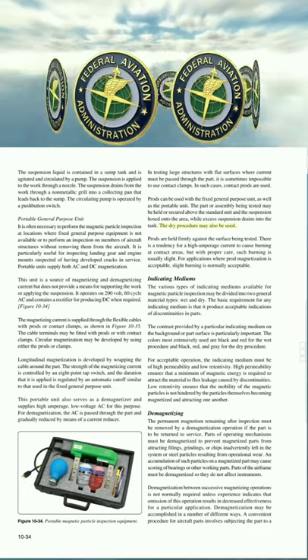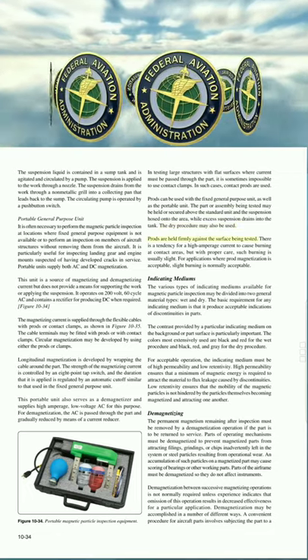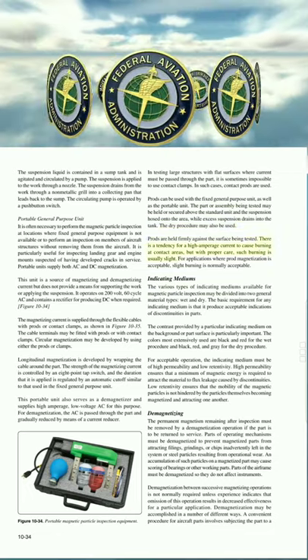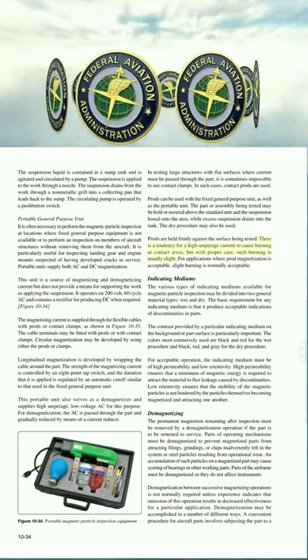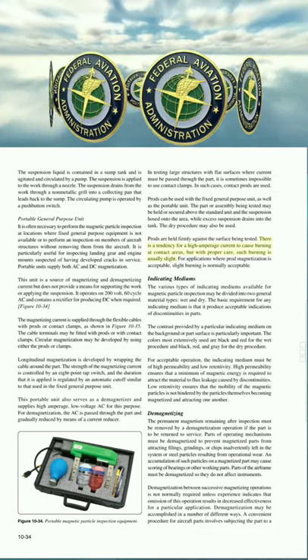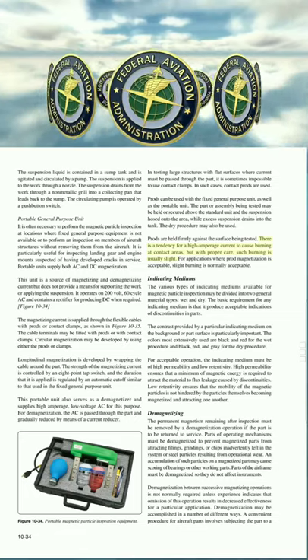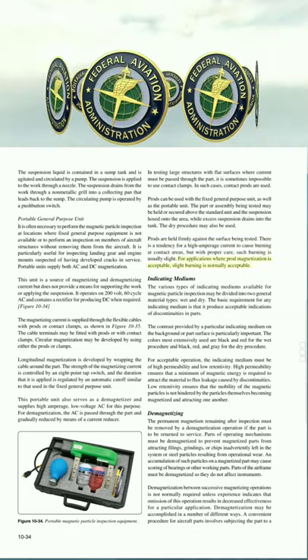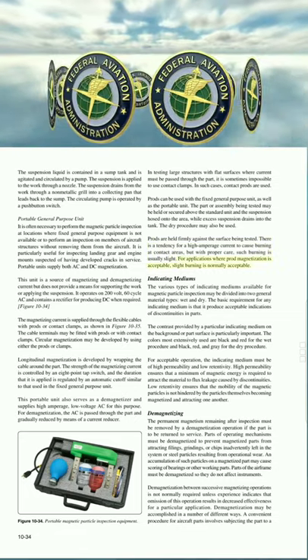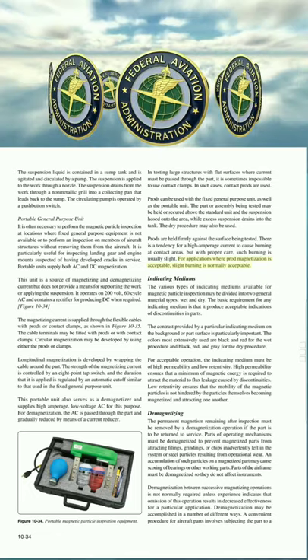The dry procedure may also be used. Prods are held firmly against the surface being tested. There is a tendency for a high amperage current to cause burning at contact areas, but with proper care, such burning is usually slight. For applications where prod magnetization is acceptable, slight burning is normally acceptable.